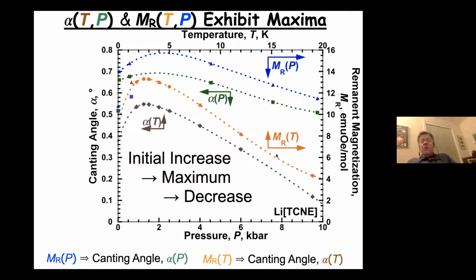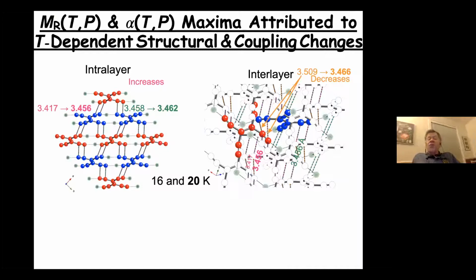We need some computational analysis, more than we have at the present time, but I'm going to give you a little insight that we have at the present time. So we have studied the structure of this interpenetrating lattice, both below TC at 16 Kelvin and approximately at TC at 20 Kelvin. The 16 Kelvin data is shown non-bolded and the 20 Kelvin data is shown bolded. And you can see the intra-layer CN interactions slightly increase in both cases for the ones at 3.42 to 3.46 angstroms, and the other one at 3.46 angstroms basically stays the same, just a slight increase.